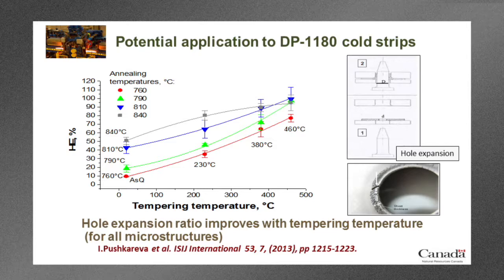That is a real problem with these steels, and the way we characterize it is we use this hole expansion coefficient. What we do is we take a thin sheet of the material in the quenched or the quenched and tempered condition. We punch a hole in it, usually about 10 millimeters in diameter, and then inside that hole we insert a conical punch with usually a 60-degree angle, and we press the punch into the material, which is going to expand the hole. The diameter will increase, and we stop the test when we see a crack that traverses the entire thickness of the material when viewed from above.